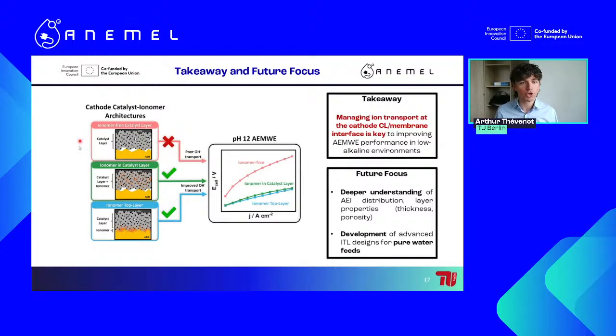So first, I showed that in a pH 12 AEM water electrolyzer, using an ionomer-free catalyst layer on the cathode would give bad results, due most likely to poor OH- transport. Therefore, to counter this, we investigated two ionomer architectures: the ionomer in the catalyst layer and the ionomer top layer. We saw that using either of them increases the performance of your whole system a lot, and the ionomer top layer is slightly better.